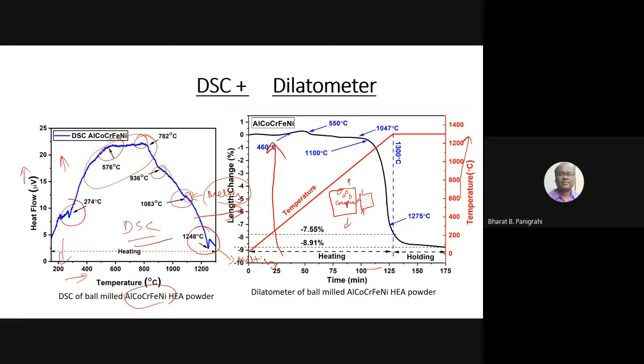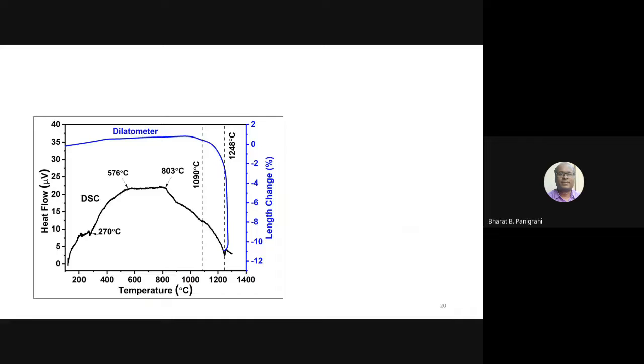And you will see that when the green compact is heated, this is the temperature, which accurately tells 1047 degrees or 1045 degrees centigrade, the shrinkage. This is the length change. You can see the y-axis is the length change, downside is shrinkage, whereas upside is expansion. This is the region where you see the huge shrinkage is happening. That means major sintering of the material is happening in this particular temperature range. I'll show a little bit more detail.